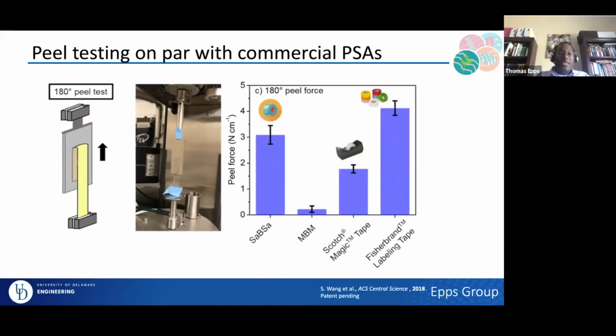So what we can do is we can take these materials, we can actually cast them onto, say, a polyethylene backing and do some ASTM standard tests. And so one that I'll show you two. So one in particular is a peel test, where we're able to take our materials, put them on either a glass slide in this particular case or stainless steel, and do a 180-degree peel test.